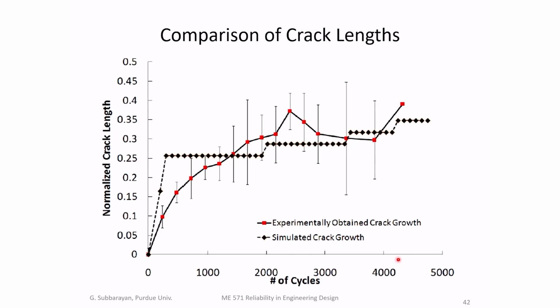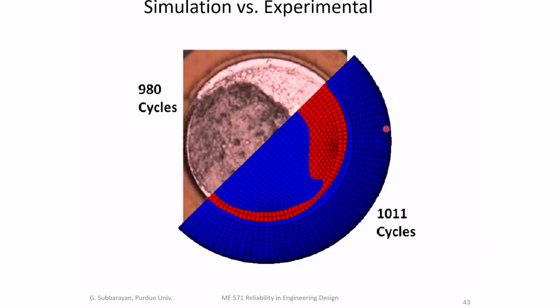And you can compare the model prediction of crack growth to the experiments. It's actually quite reasonable. And finally, if you look at the crack front, they compare very well within 10%, which is usually very, very good for fatigue prediction. So the key point of this case study is that in order for you to characterize life, you need to take a sample, cycle them, test them to failure, and then you need to study the physics to develop a model.